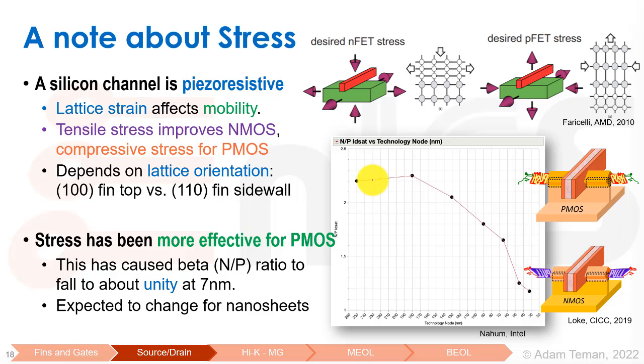You can see this graph here that shows the N/P ratio, or what we call the beta ratio, which used to be, when we teach it in our textbooks, we say that the NMOSs have mobility that's like 3 times as high as the PMOSs. Well, that's been going down for many generations, and the main reason is this stress. And really, at 7 nanometers, it's fallen to about unity. So we can have our PMOS and our NMOS be equivalent to each other, rather than have double the size PMOSs than NMOSs, as we learned in our previous courses.